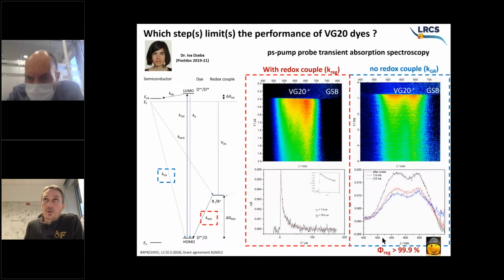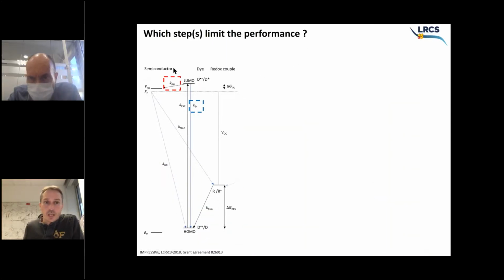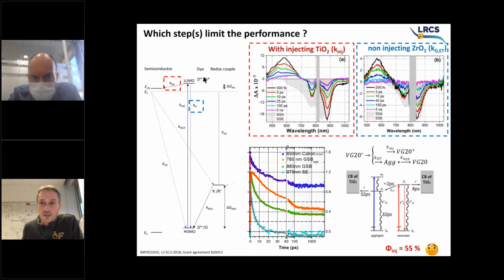So if you want to determine the regeneration quantum yield, then it's very simple, it is the ratio between those two numbers, and one can easily see that this is 1,000 times faster than this. So the regeneration of the dye is 99.9%. So everything goes very well for regeneration. Now what happens for the injection? The scheme is more complicated.